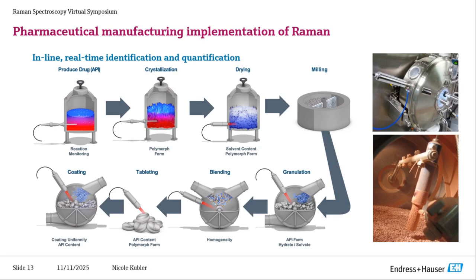Moving into the granulation, Raman detects hydrate or solvate formation during wet granulation and maintains correct API form for downstream processing. In the blending stages, Raman checks blend uniformity by mapping API distribution and excipients, which reduces risks of content variability in final dosage. Raman can also be utilized to monitor coating thickness and uniformity in real time, confirming API presence in coated layers if applicable.